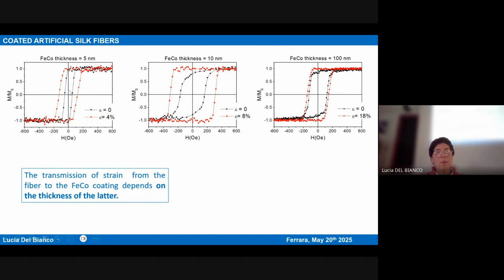And you see that also at zero strain, the fibers are different. I mean, the shape of the hysteresis loop is different. The coercivity is different, even without strain. But when you apply a strain, you observe different behaviors. For instance, in this case, a strain of only 4% is sufficient to more than double the coercivity.